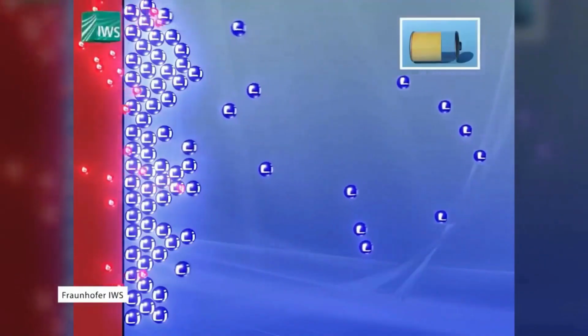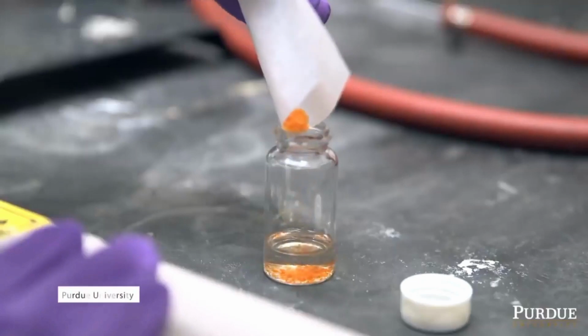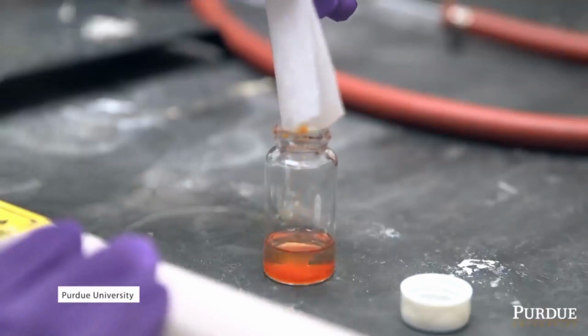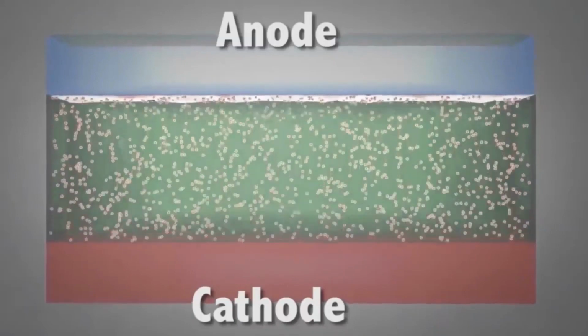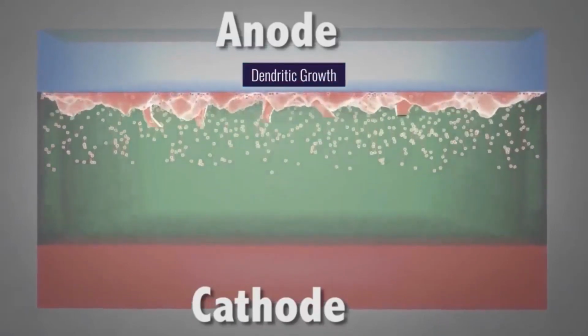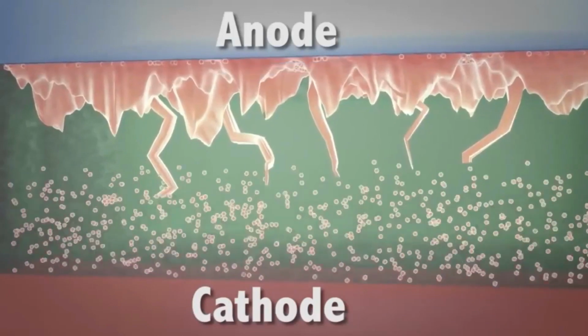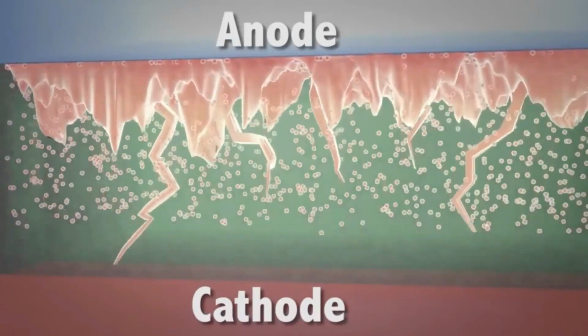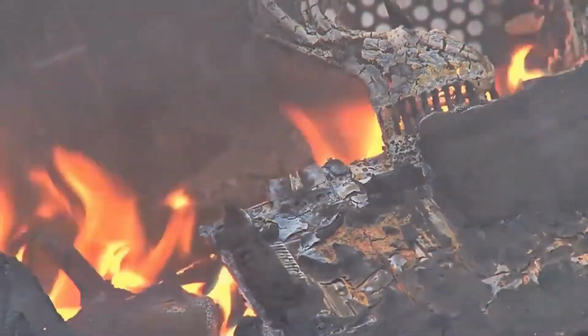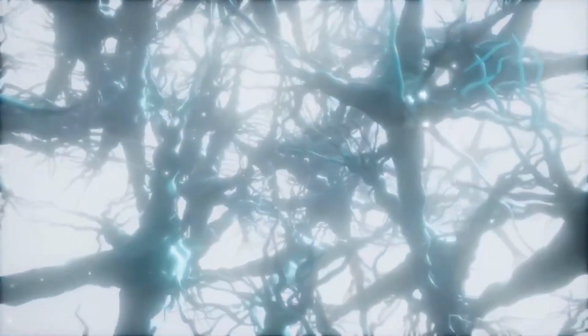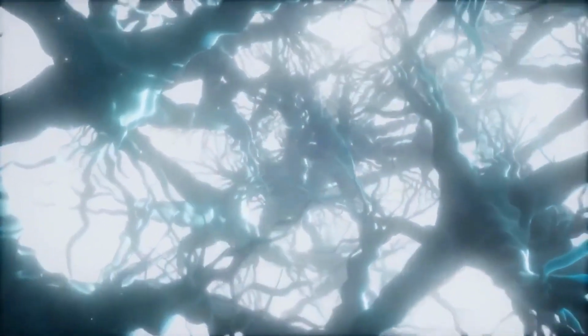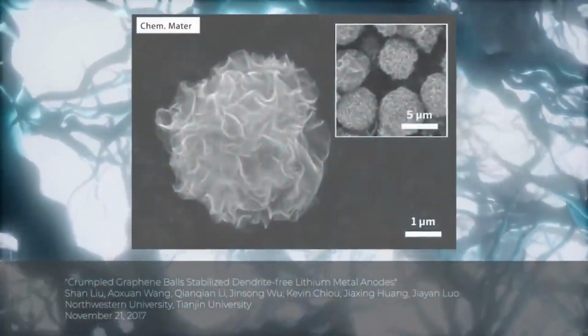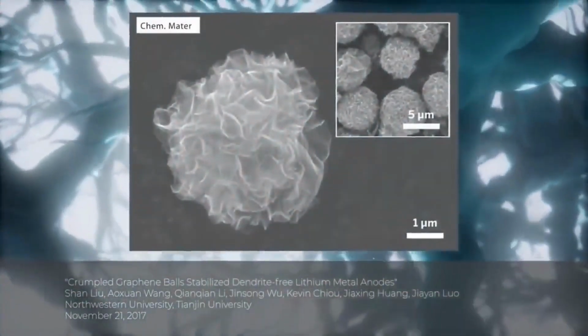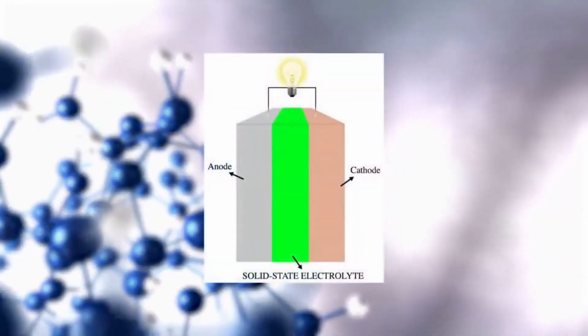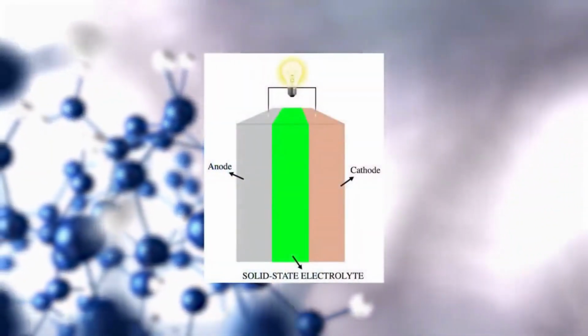One approach to solving this is to bind the cathodes with different polymers and to reduce their thickness so that the absolute change in dimension is not so extreme. Many lithium-based batteries also must deal with dendritic growth, thin fingers of metal which grow away from the surface and can eventually reach across to the cathode, creating a short circuit and rapid discharge. This is the same thermal runaway malfunction which has caused lithium-ion battery fires in the past, so research for coping with this effect can be carried over to lithium-sulfur technology, including exciting uses of graphene and other nanostructures to act as scaffolds for the deposition of lithium. Solid-state electrolytes could also offer solutions to these issues.